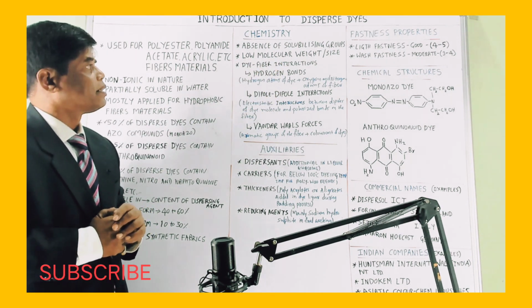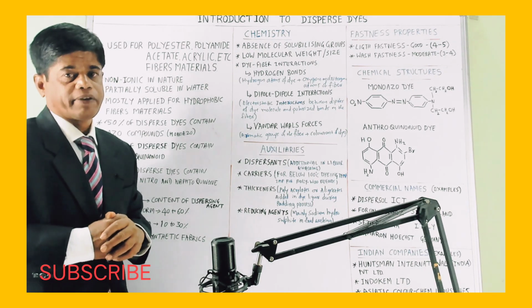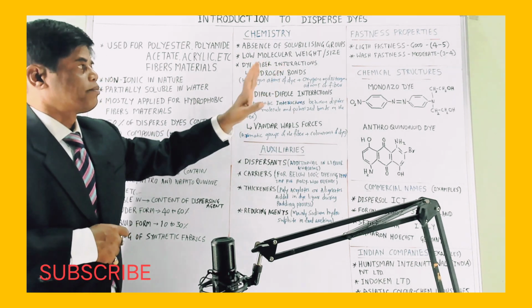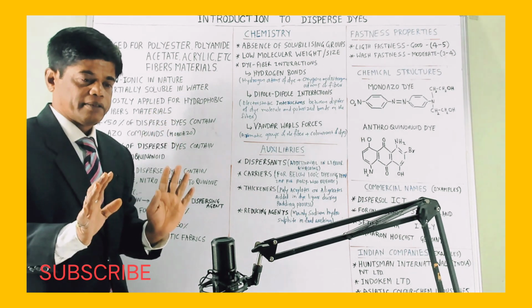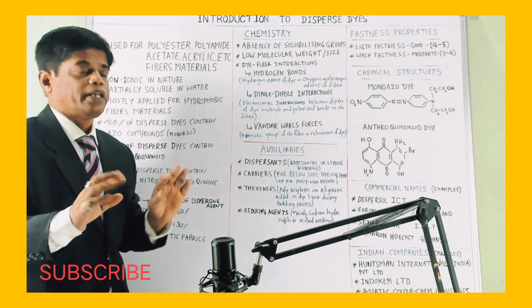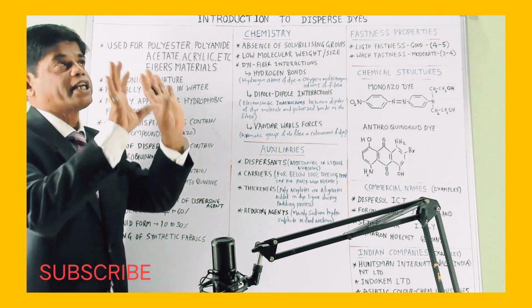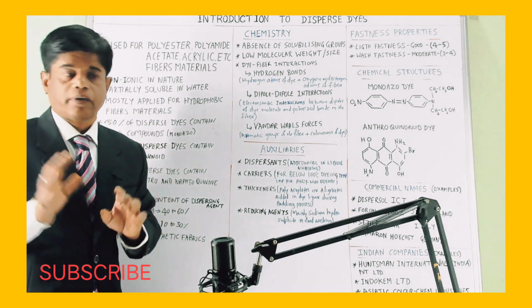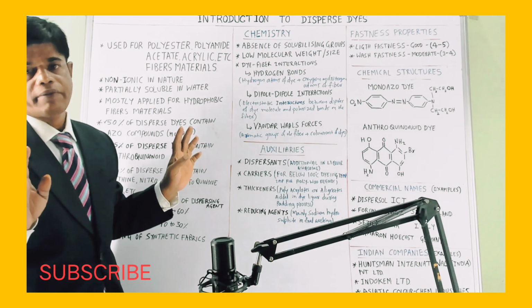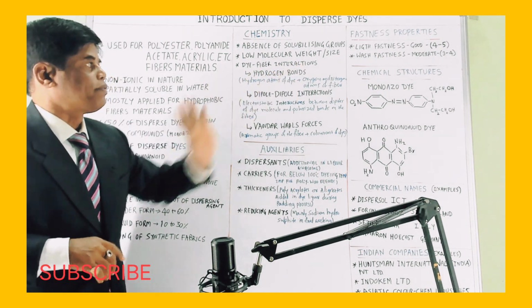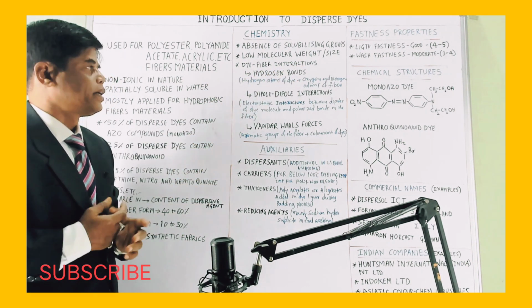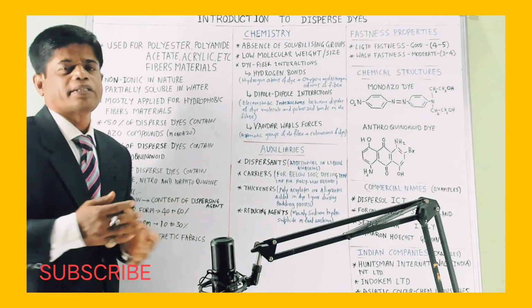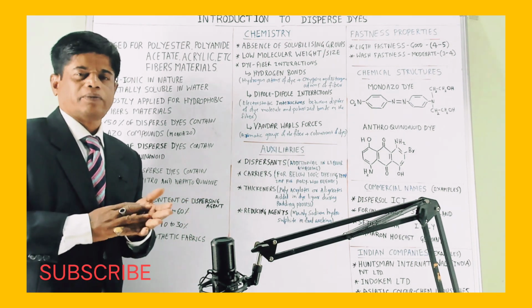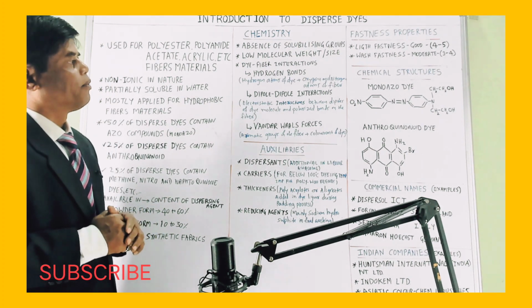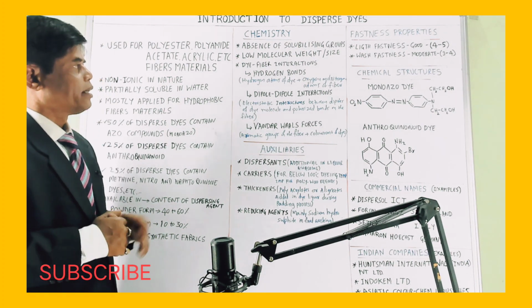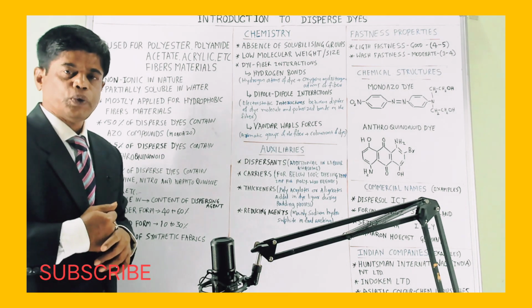Dispersed dyes dyed on polyester fibers have good light fastness. Light fastness means that if the dyed polyester or acetate fabric is exposed for a long time to sunlight or heavy light, the color will not fade. The grade is 4 to 5. Wash fastness is moderate, 3 to 4. You can also see that polyester or even nylon usually bleeds in washing, though not compared to cotton. So the light fastness and wash fastness properties are good.